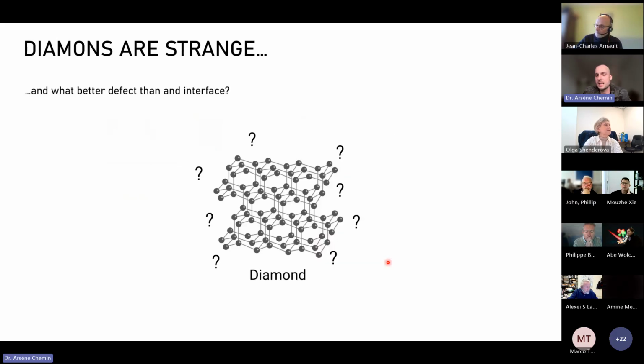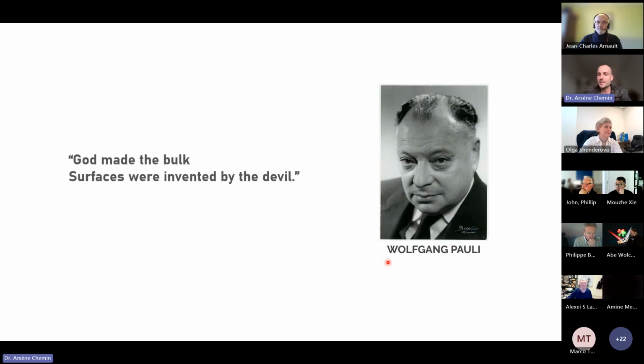But what better defect than an interface? When you think about it, an interface is nothing more than a huge amount of defects. Every time you cut a crystal, you necessarily create defects. You have to break bonds, you have to reorganize the surface, you have to create lots of things that can be excited, that can lead to charge separation, charge trapping, and interaction with the surrounding environment. And those interfaces are the source of so many interesting behaviors in diamonds. But as Wolfgang Pauli said, if God made the bulk, surfaces were invented by the devil.